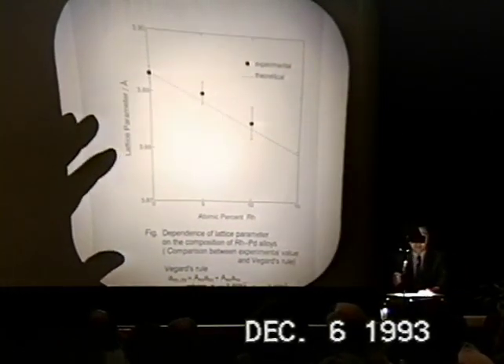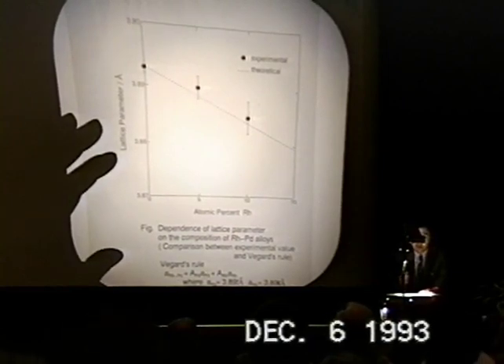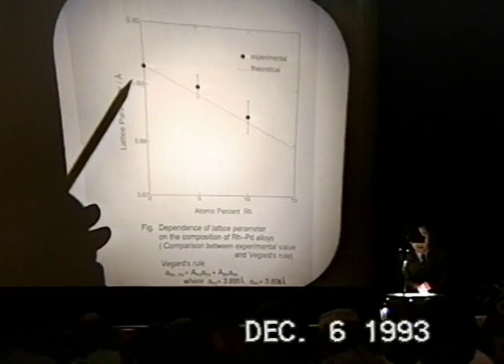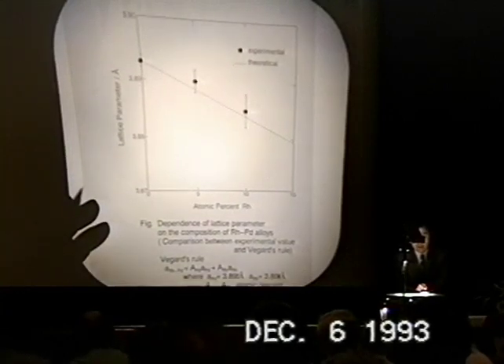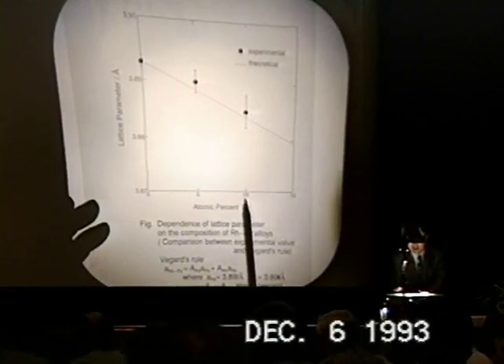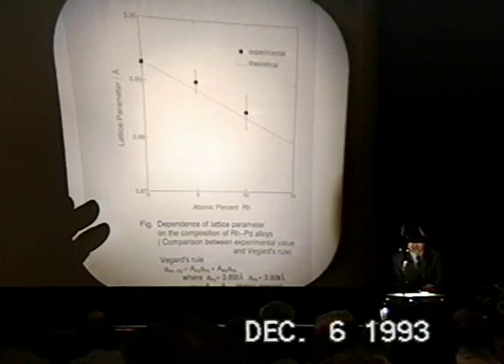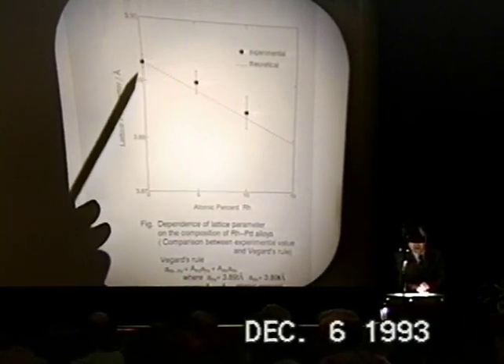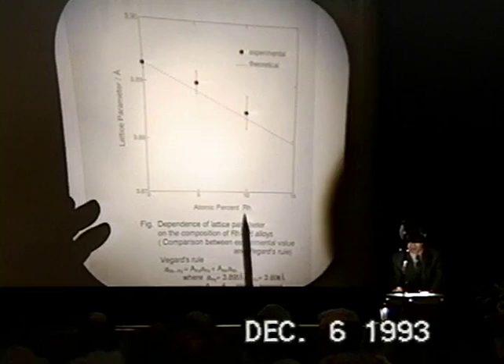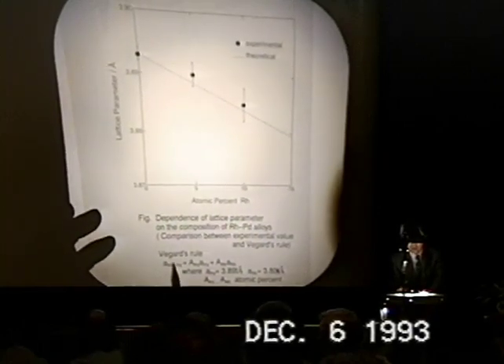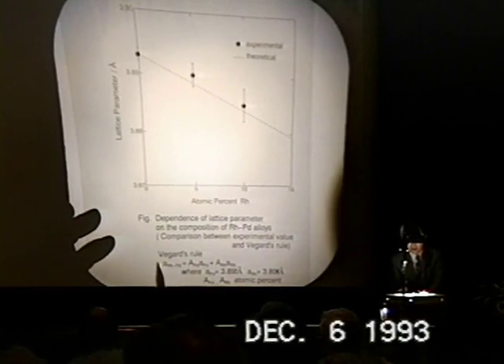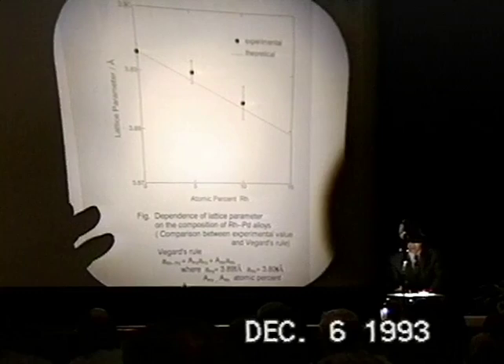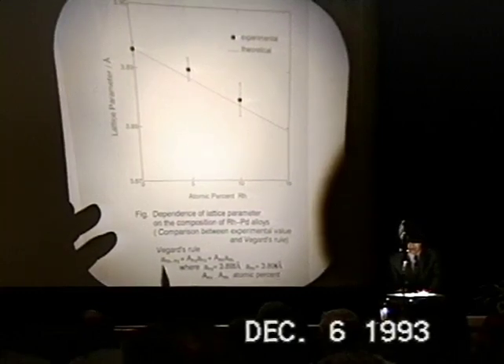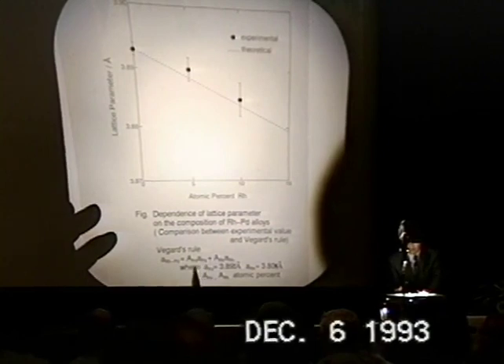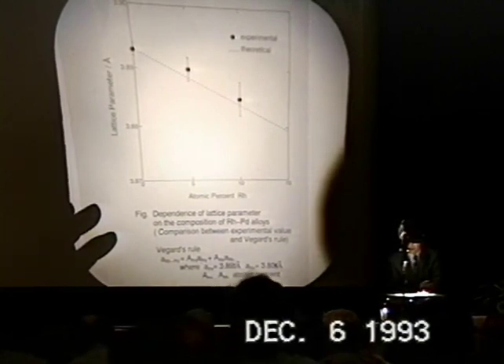And I'm showing you here some X-ray diffraction data to show the change of lattice parameters of our alloys, which was only 5 and 10%. We are going to have 20 and 30% rhodium palladium alloys shortly, but if we plot the lattice parameter as a function of atomic percent of rhodium, we can see a very good coincidence with what is called Vegard's rule, showing the linear relationship between the lattice constant of the alloy and each respective palladium and also rhodium lattice constants.